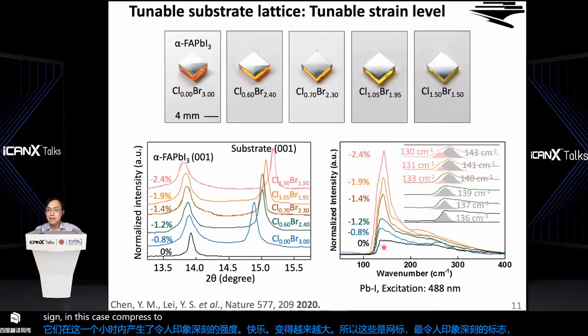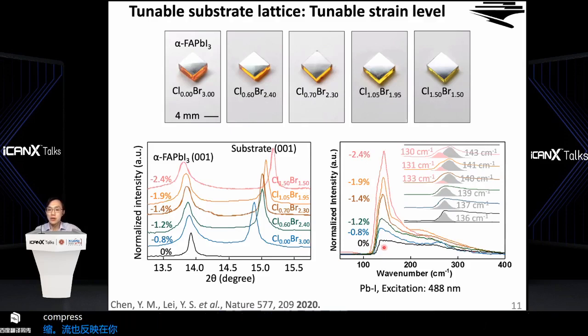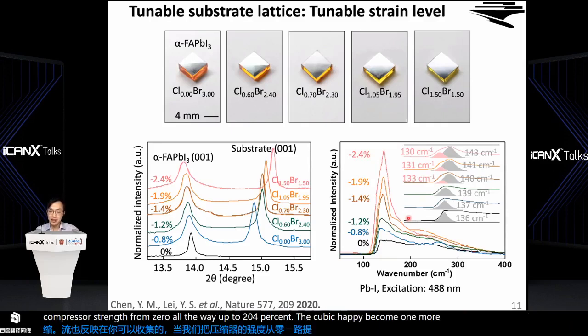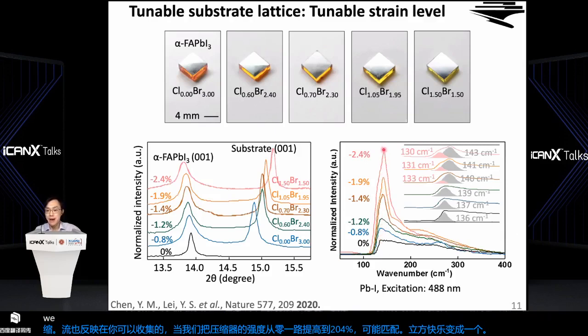As you can probably imagine, when we increase the compressive strain from 0 all the way up to 2.4%, the cubic alpha FAPI becomes more and more tetragonal because it's in-plane compressive. So out-of-plane is tensile, right? So it becomes more and more tetragonal. Then it loses its symmetry, then becomes more and more Raman active. That's why the peak intensity is higher when we increase the compressive strain magnitude.